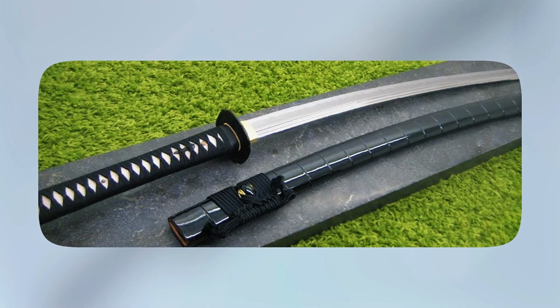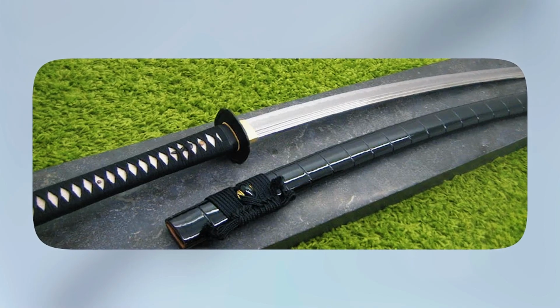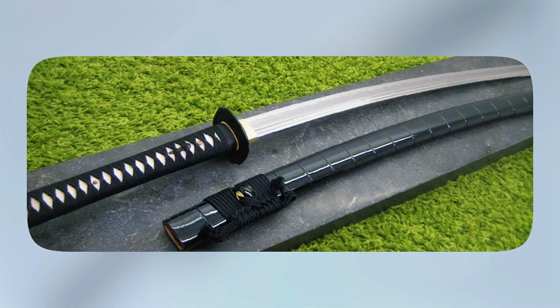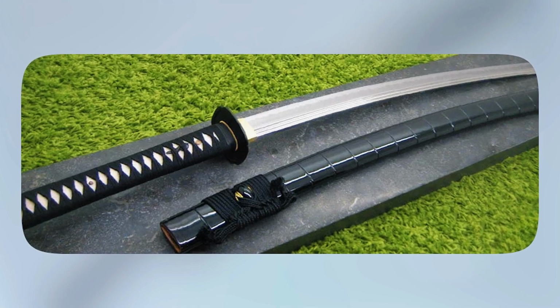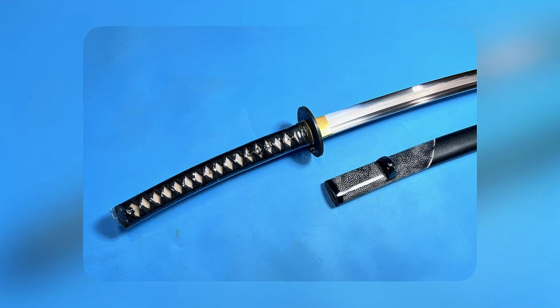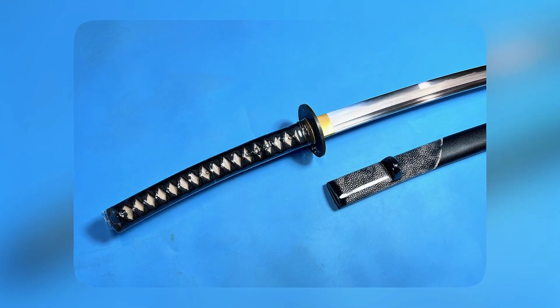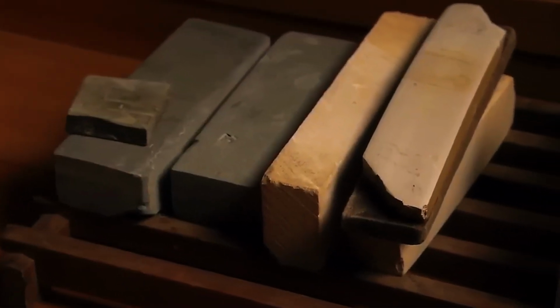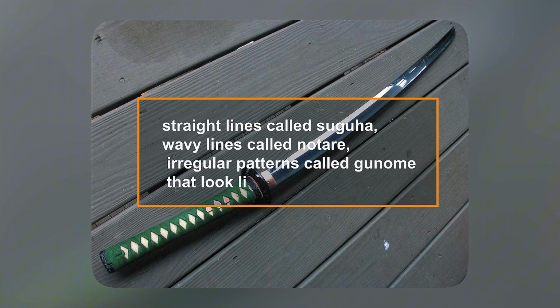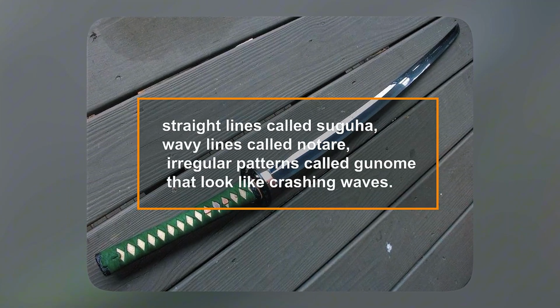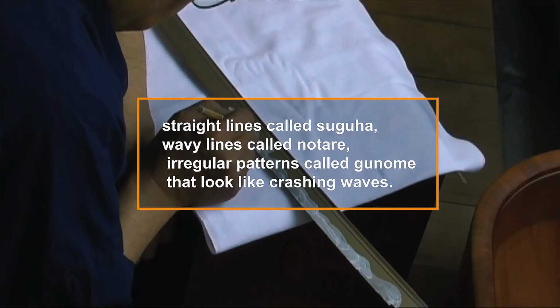The hard martensite along the edge polishes to a bright, almost white color, like a mirror. The softer pearlite in the spine polishes darker, cloudier. The boundary between them, the hamon, becomes visible as a distinct line running the length of the blade. Different clay patterns create different hamon styles. Straight lines called suguha, wavy lines called notare, irregular patterns called gunome that look like crashing waves.